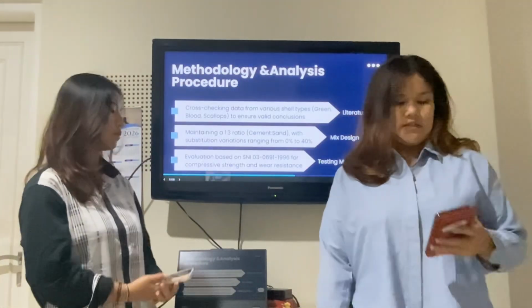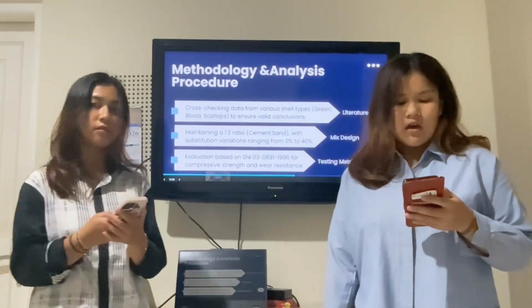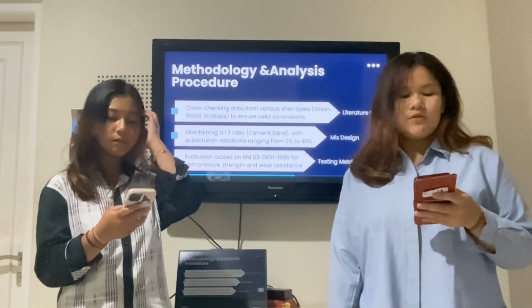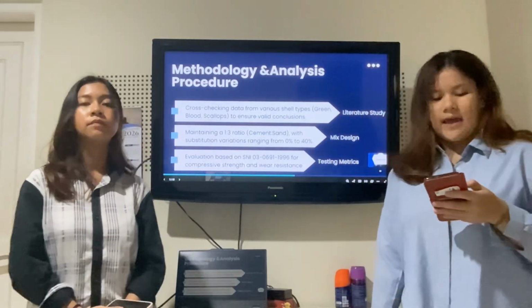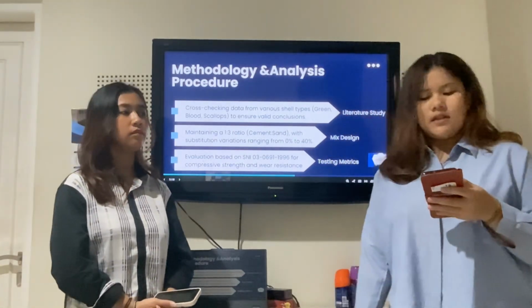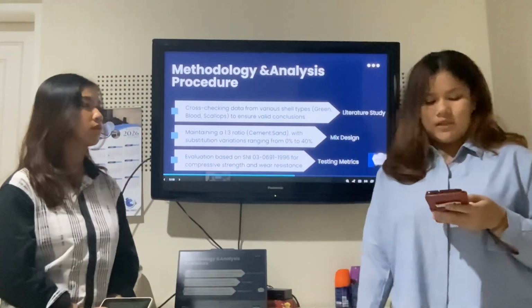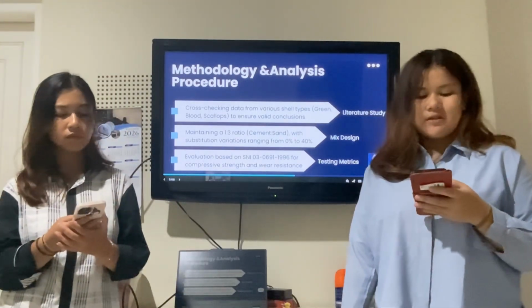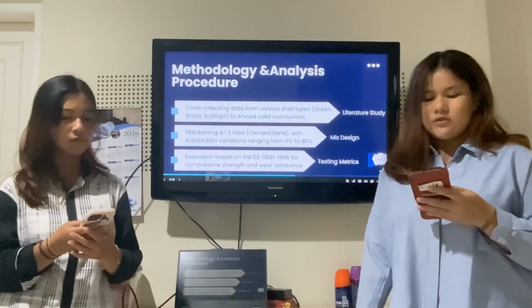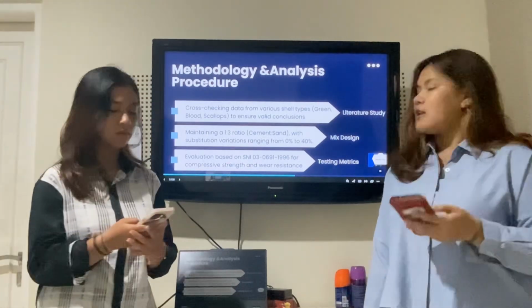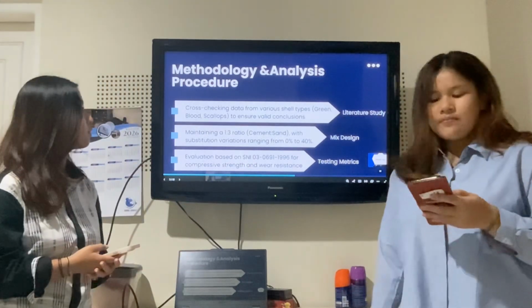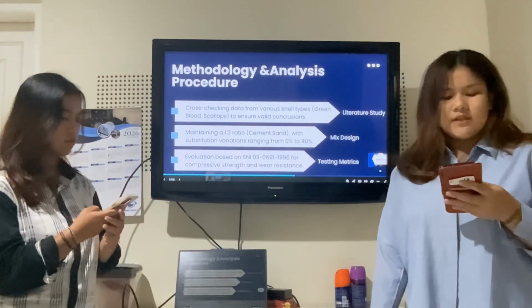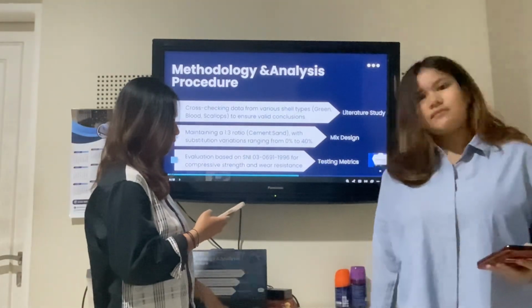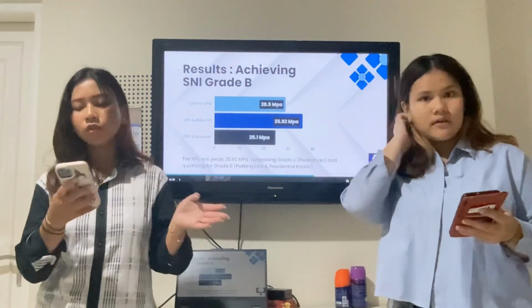For our methodology, we use a consistent 1:3 ratio of cement to sand. We then created several variations, replacing the sand with the shell powder at concentrations of 0%, 10%, 20%, 30%, and 40% to find the sweet spot. Now, let's look at the data.